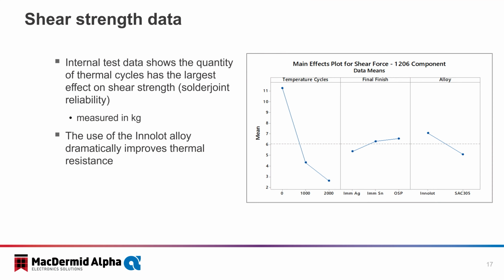And just one more look at solder joint reliability. It can be seen through shear strength. In our internal testing, the data shows that the quantity of thermal cycles has the greatest effect on shear strength, which is measured in kilograms, but that the use of the Innolot alloy drastically improves thermal resistance.